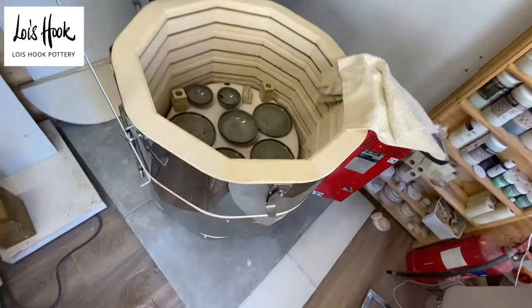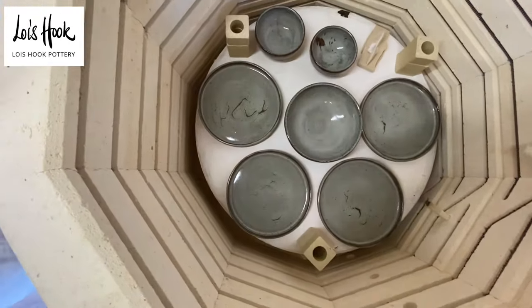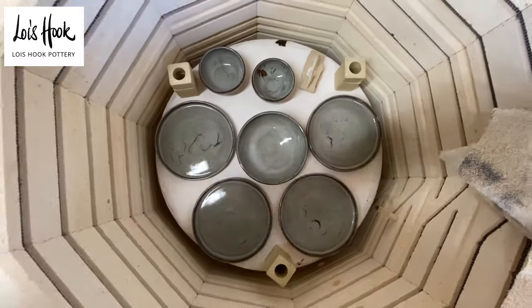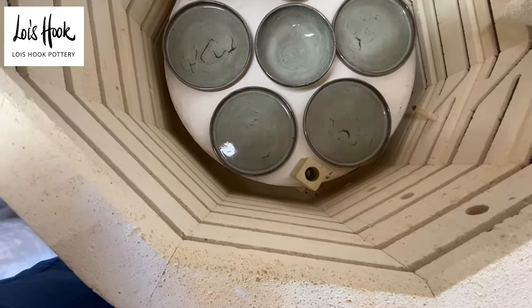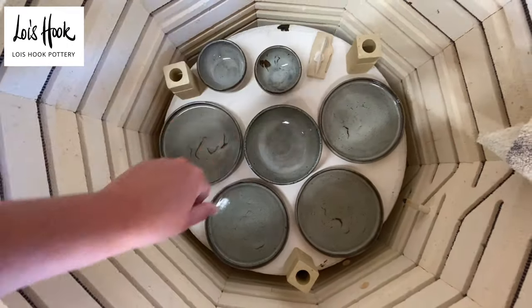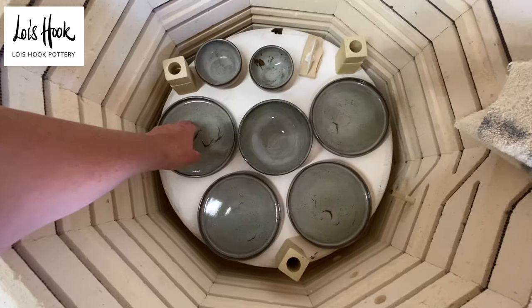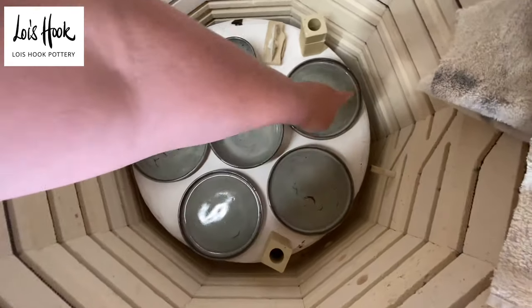Underneath here I've got some reactions that I don't like particularly. It might be that I have to refire them. This other cone is showing me that the seven has gone all the way over — so this is the layer below. We've got some glaze shifts here. I don't know what the bottom layer is going to be like. It may be that I can just refire these slightly cooler and see what we get, because the glaze has shifted off the rim.